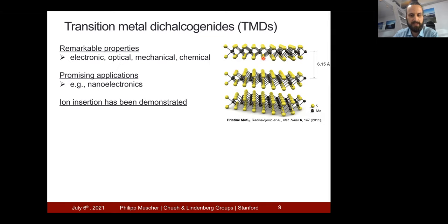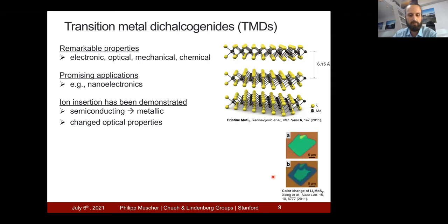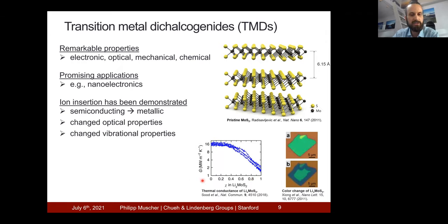So ions can be inserted in this van der Waals gap between the layers. And then for the example of molybdenum disulfide, which is shown over here, we see a transition from the semiconducting to the metallic state. We see changed optical properties, as you can see on the bottom right, where the color of the material changes as ions are inserted from towards the edges of the material. We see changed vibrational properties, which in turn lead to the one order of magnitude reduction of the thermal conductance of the material with lithium ion insertion.